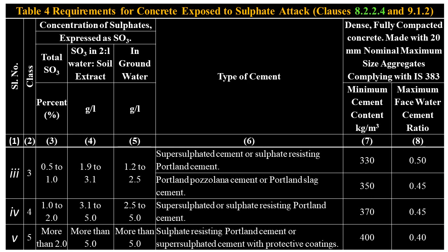Type of cements: supersulfated cement, or sulfate-resisting Portland cement. Minimum cement content, 330 kilograms per cubic meter. Maximum free water cement ratio, 0.5.